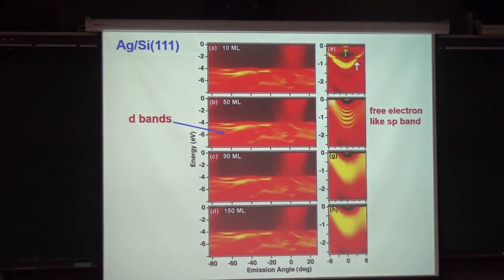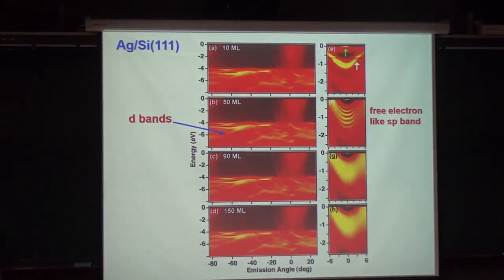Okay, so I talked about this paraboloidal band. So this is silver film again on silicon (111). So this is 10 layers, 50 layers, 90 layers, 150 layers, to see the evolution. Okay, 10 layers, you got to see this guy here, parabolic band with some kind of interesting thing that has something to do with the substrate band edge, silicon band edge.